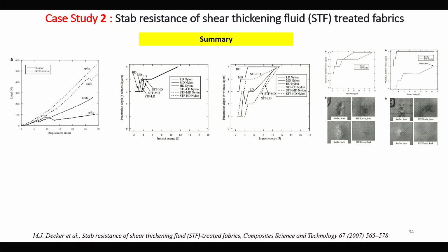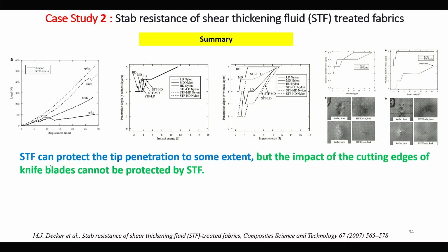The summary for this study is that STF can protect from the tip penetration, basically. So, for spikes it can protect, but the impact from the cutting edge of the knife cannot be protected by STF.